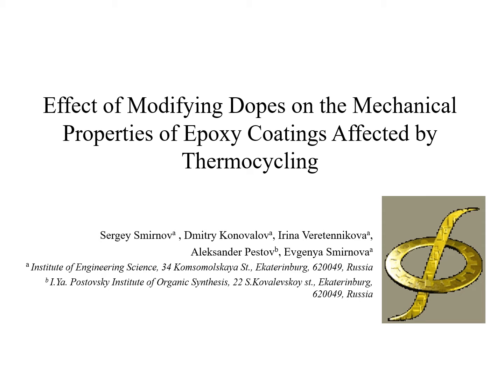The aim of this work is to study the effect of nano-sized oxides, namely titanium dioxide, silicon dioxide, and zinc oxide, used as modifiers of epoxy lacquer based on ED20 epoxy resin, on the elastic modulus, micro-hardness, and creep of the resulting coating after multiple temperature differences.